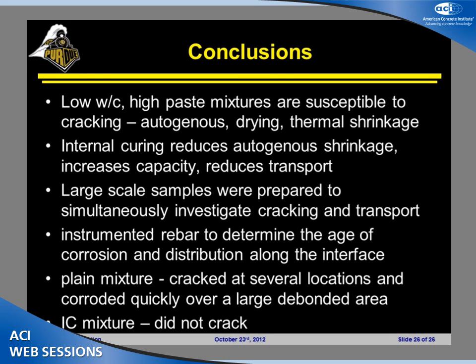Yeah, actually, where we started to look at this issue, we've been looking at monitoring crack widths for quite a while. And what we really started to do is we were doing some work with the Danish Technical University, and we were actually able to start to image what was happening along the bar. What's interesting is we focus a lot on the width of the crack, but really where things start to get interesting is where the width of the cracks starts to stay stable, but you start to get that debonding. And that's where we really started to develop this idea of using the sensors along the bar, because this starts to explain a lot of things that we can't explain just by looking at crack widths.